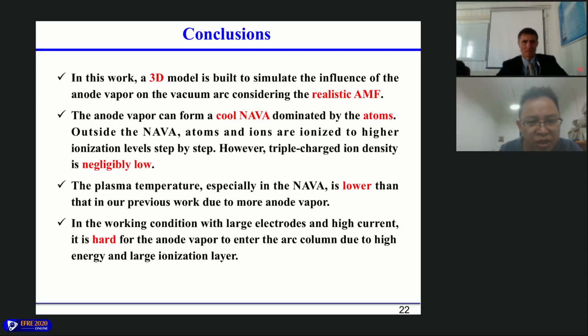The plasma temperature, especially in the anode vapor region, is lower than that in our previous work, with a smaller diameter, due to more anode vapor. In the current working condition with larger electrodes and high current, it is very hard for anode vapor to enter into the arc column due to the high energy and larger ionization layer.